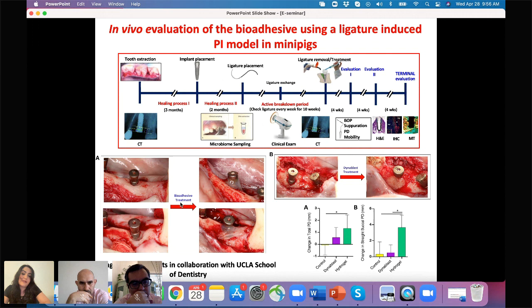This is the implant that we treated with the bioadhesive group. This is the hydrogel around the implant. It remained around the implant and helped bone regeneration. And this is our group that was treated with the bone graft. And then when we look at the bone formation around the implant, the hydrogel group was more effective as compared to the bone graft and the control group, which was the untreated group. So we have lots of data with microCT analysis and for the immunostaining that hopefully will be published soon.